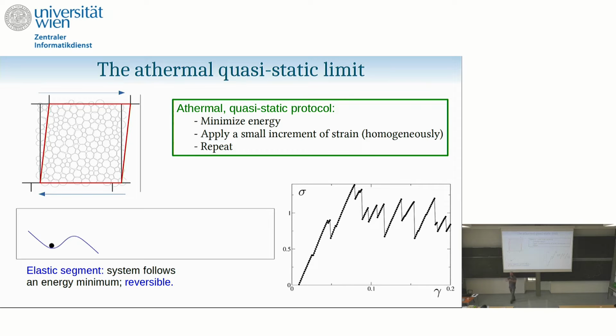So around the minimum, you have a domain of the potential energy landscape, a basin of attraction, where every system will converge. So if you take a system in a minimum and you bring it a bit out of the minimum and let it relax and re-minimize, it will come back to the same point every time, okay? So now what happens when you strain? If you apply a very small amount of strain, you will distort the potential energy surface. You won't do anything catastrophic. Small means that you very continuously change the minimum and its basin of attraction. When you do this, the position of the minimum changes. So you strain your system a bit and let it relax, and it will follow adiabatically the local minimum where the system starts from. You can repeat.